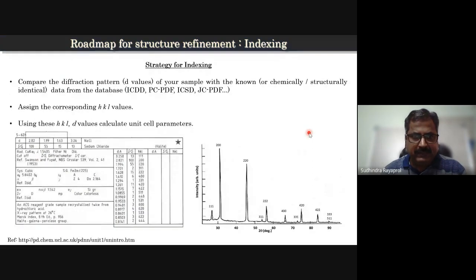So what we need to do is, if you look at the diffraction databases such as ICDD, PCPDF, or JCPDF, what they list are the HKL values of the strongest Bragg peaks and the angle or d values. What we measure is generally in 2 theta, so using Bragg's equation, you can convert it into d-spacings. You compare with the literature values, assign these Miller indices to these Bragg peaks, and you can mark the d values from your observed data and the HKL values from the database. Using these HKL and d values, you can determine the cell parameters. So that is the purpose of doing indexing.